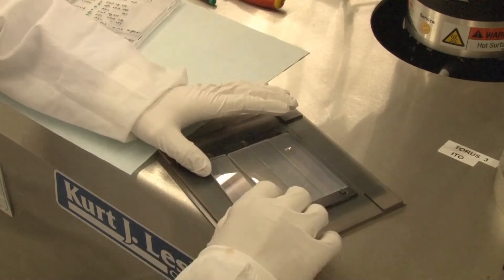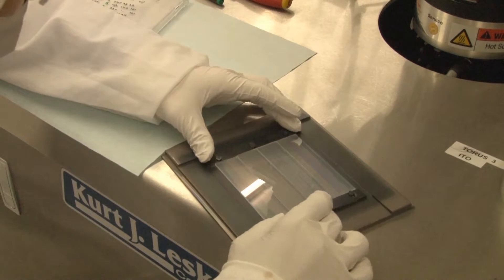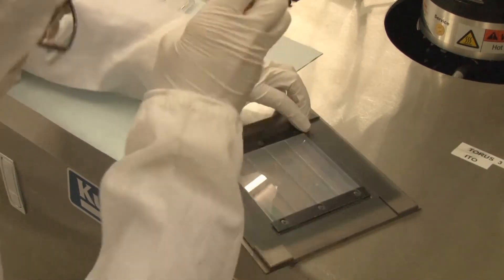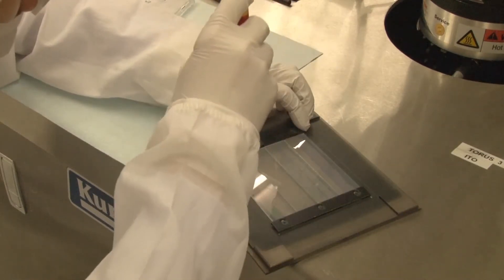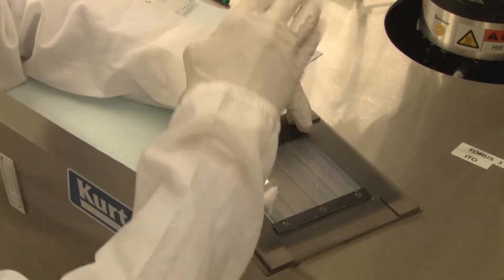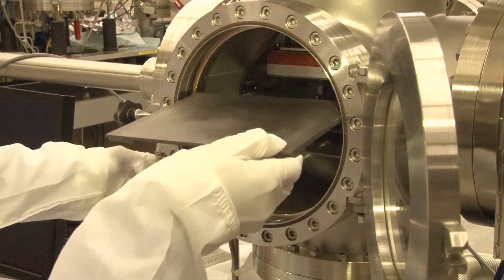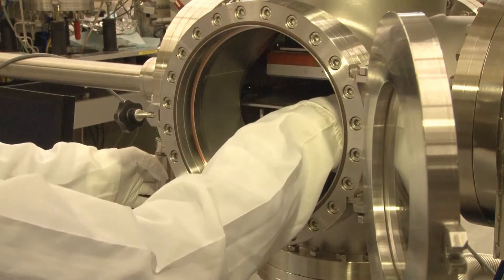Here we use a substrate that is coming from the Japanese Asahi Glass Company and already has a TCO coating on it. The TCO coating is a fluorine-doped tin oxide and is responsible for the hazy color. In this movie, we deposited a thin zinc oxide layer on top of the Asahi substrate to protect the tin oxide from the next processing step.